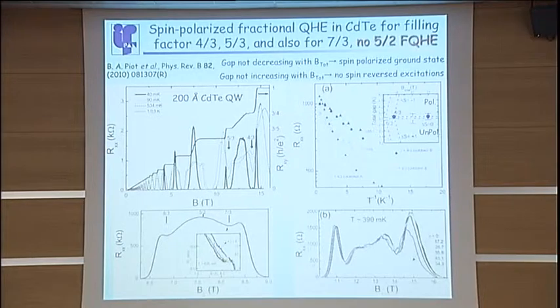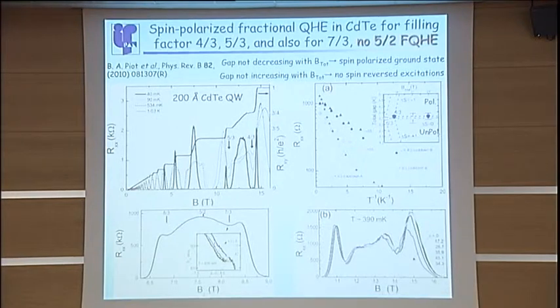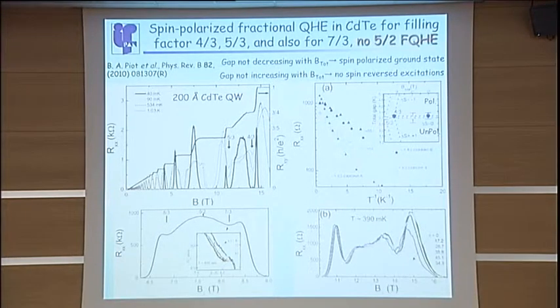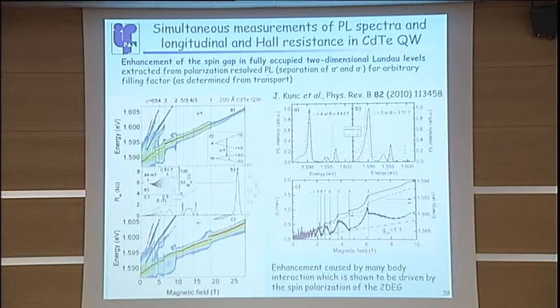interaction-driven effects. So, for instance, the fractional quantum Hall effect, and this has been measured by the group of Professor Marek Potemski. They have clearly shown that there are well-developed 5/3 and 4/3 fractional quantum Hall effect states, and also, by performing studies as a function of angle, so increasing the in-plane magnetic field, they have shown the typical experiment to show that this ground state is spin polarized, which is of course expected because our materials have a larger g factor than gallium arsenide. Now also, which is not typical for gallium arsenide, I was told that in the case of our structure, it was possible to perform simultaneous measurements of optical and transport properties on the very same sample at the same time.